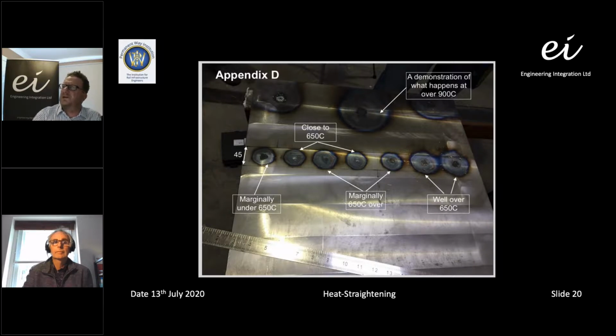So we can actually define the heat that we're putting into the structure by the circumference of the heating pattern that we've got. And you can see there at the top of the image, we've got some temperatures where we've taken it up to 900 degrees C. Obviously this is a test panel, not a final element or within a bridge structure. And you can see there the heating pattern is probably, I don't know, 120 millimeters, 130 millimeters in diameter. And you can see there it's obviously excessive heat has been applied at that particular location. So we use those heating patterns to define the heat that's been applied into the structure.